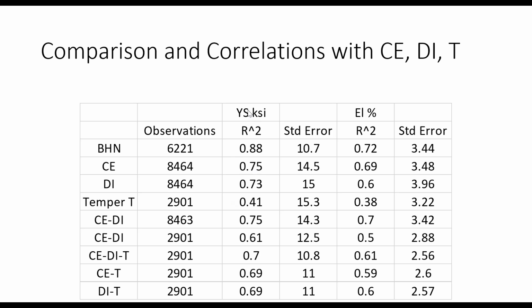One of the challenges is when I look at R squared, this is how close all the points are to the line. This shows how far away on average the points are. This is a fraction, so 1 would mean it's perfect, 0 means it's nothing, but it doesn't have units. This is actually in KSI. So if I take the Brinell hardness, I have an 88% assurance that I'm going to get an accurate prediction. And in terms of precision, I expect any individual data point, at one standard deviation, 66% of the data points will be within 11 KSI of that line. So that's really a useful thing.